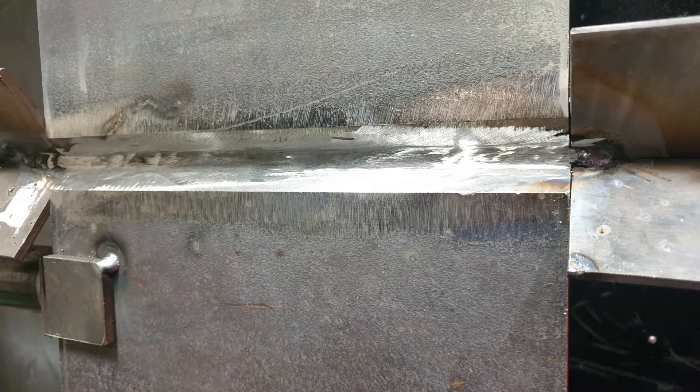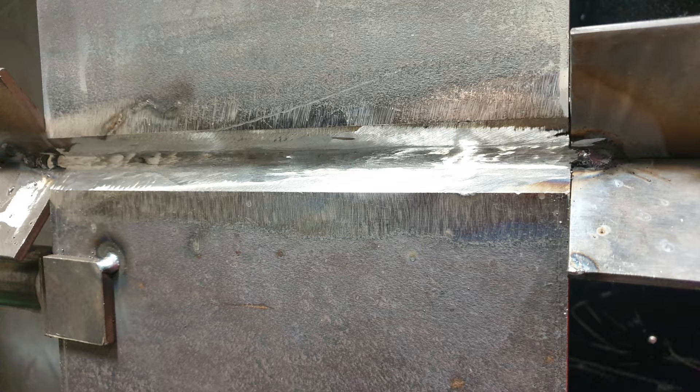There's a picture of a finished run. We've got a nice little bead, nice and consistent. Moving forward we now grind back. A lot of people don't do this, but we always do just to make sure you've got no slag or anything that's going to possibly give you troubles when you put that hot pass over the top.